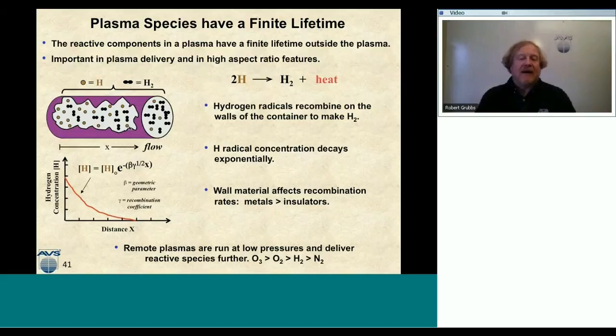And so ozone lasts a very long time. It seems that nitrogen is a very short-lived radical. Next would be oxygen, and then hydrogen. So N2 plasmas are very difficult to use remotely. The nitrogen radicals don't live very long, just because of that triple bond between each of the nitrogen atoms.